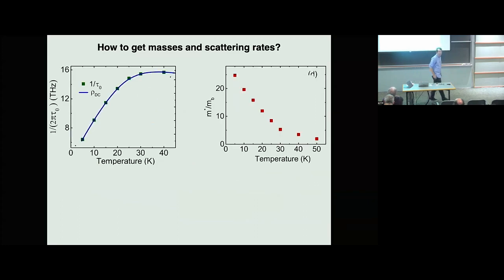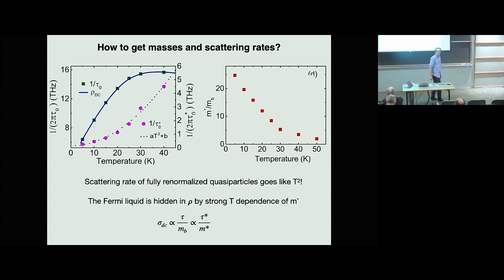But how can we rationalize that with a linear in T resistivity? We have linear in T resistivity, which has been heralded as non-Fermi liquid behavior, and that's a plot of 1 over tau here in the zero frequency limit, the green dots, and then rho dc just normalized, and you can see they're on top of each other. That linearity is the linear in T resistivity that's discussed. But the point I was making is that if we really want to consider the renormalized heavy fermion quasiparticles, we need to take into account 1 over tau star. If we're going to talk about masses at all, we have to keep Boltzmann transport in the back of our heads, and that's 1 over tau star right there, which is consistent with a T-squared dependence of the scattering rate of the fully normalized quasiparticles. My claim is that the Fermi liquid in this system is hidden in the resistivity by the strong temperature dependence of M star. That's the temperature dependence of M star there.